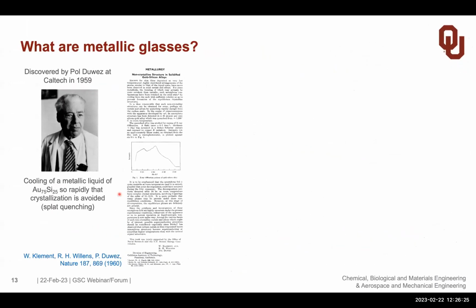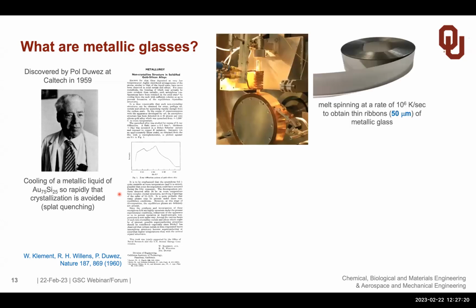So what are metallic glasses? This was discovered only in the late 50s by Pol Duwez, who was a professor at Caltech. What he did was rapidly quench an alloy of gold and silicon, 75% gold, by splat quenching. He took a droplet of a liquid metal, which of course has highly mobile atoms, and splat quenched it between two plates. And what he obtained was a non-crystalline material. It was something not known at that time, because a glass with an amorphous structure was only known from oxide glasses, which we have used for thousands of years. But it was not possible before that experiment to do that also for metallic material.